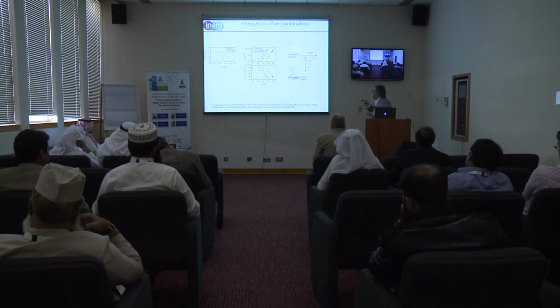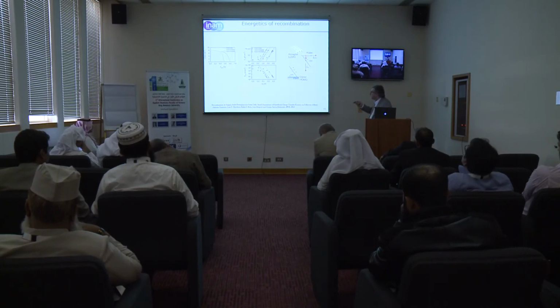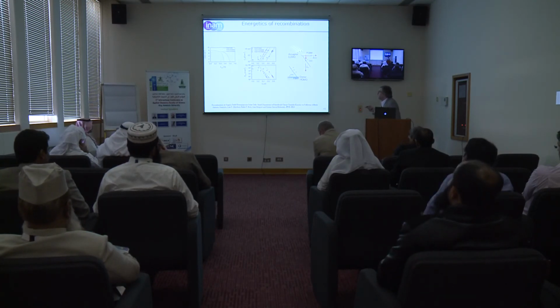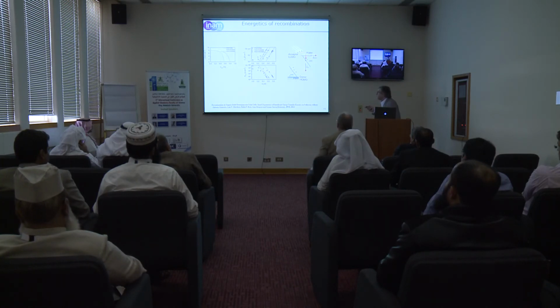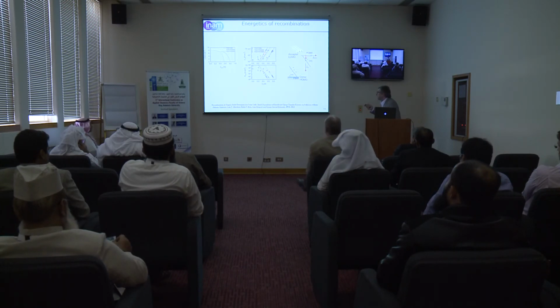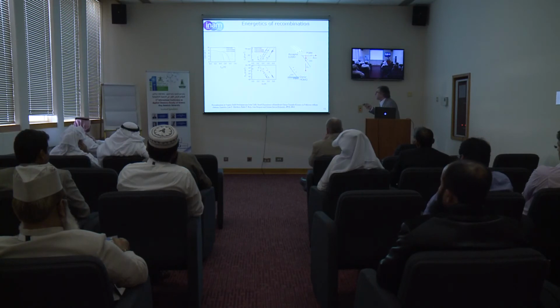You can see here the energetics of this PCBM with the density of states, then you have another fullerene with its density of states. We can see here the chemical capacitance, and when we compare different types of fullerenes, the higher one is ICBA here, so it will give the higher voltage.